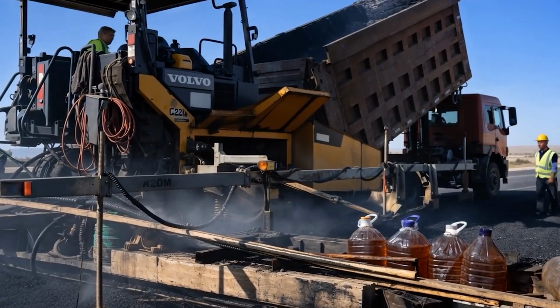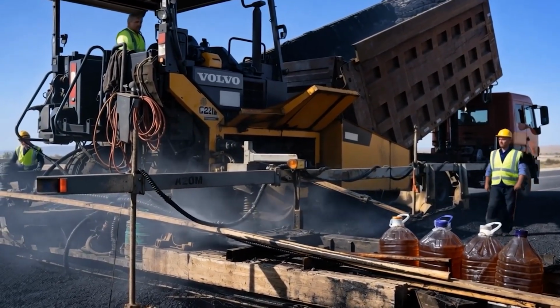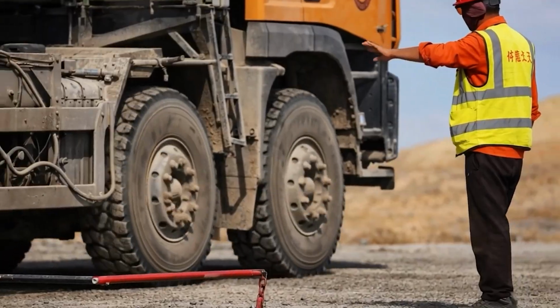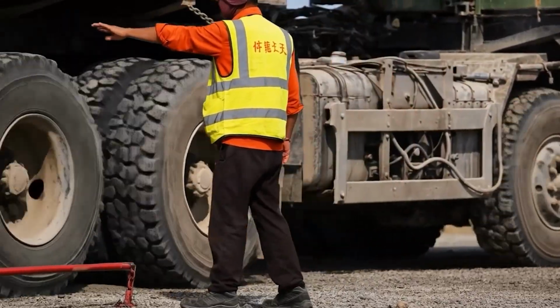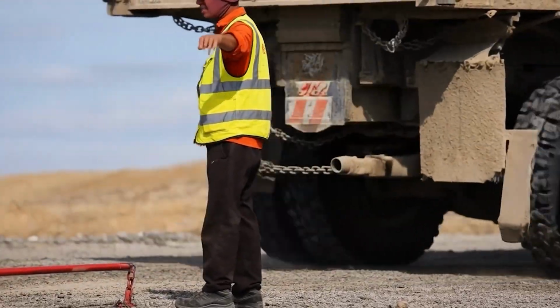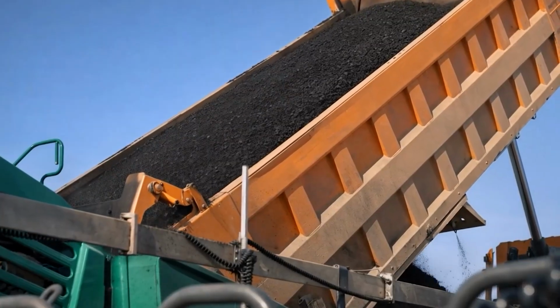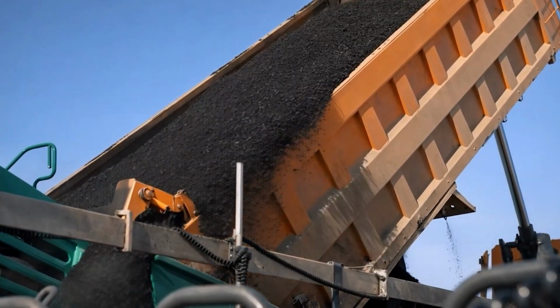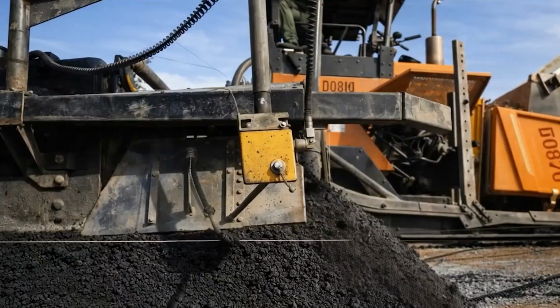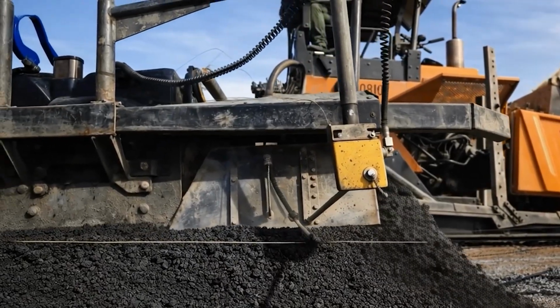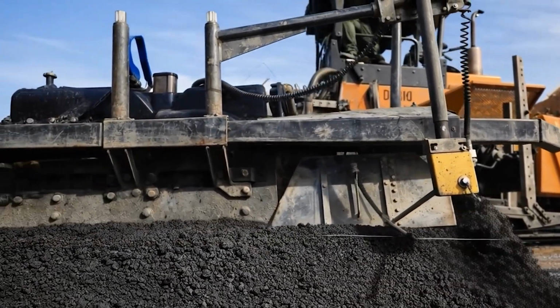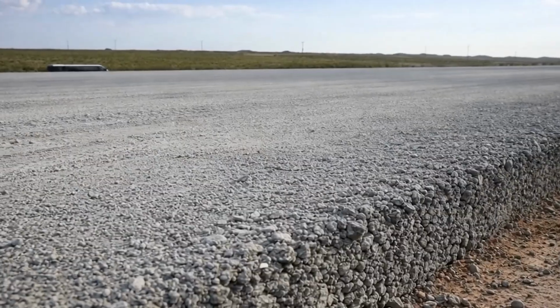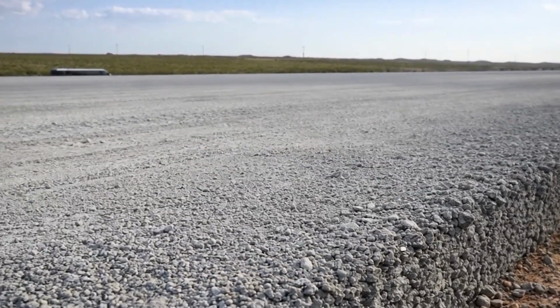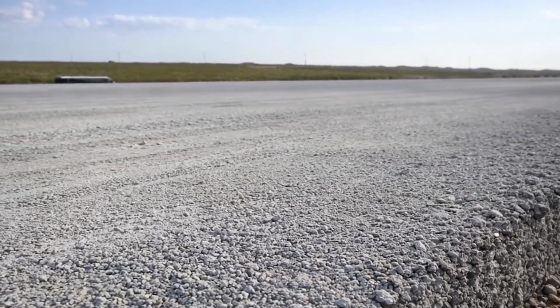At the edge of the desert, mobile asphalt plants went into operation. Stone, sand, and polymer-modified bitumen were heated to almost 170 degrees Celsius. From there, insulated tankers delivered the hot mix non-stop directly to the placement site. Asphalt pavers distributed the scorching material in layers about 6 centimeters thick. Then, almost closely behind them, rollers compacted the pavement before it began to cool.